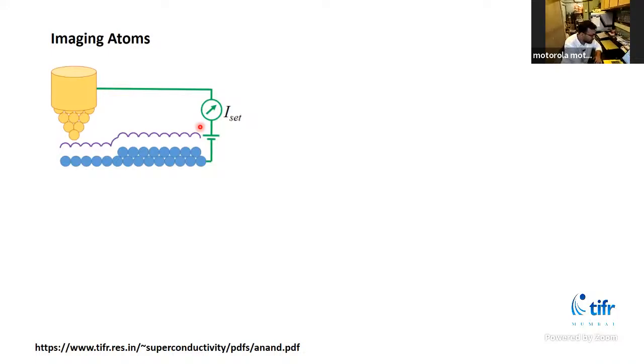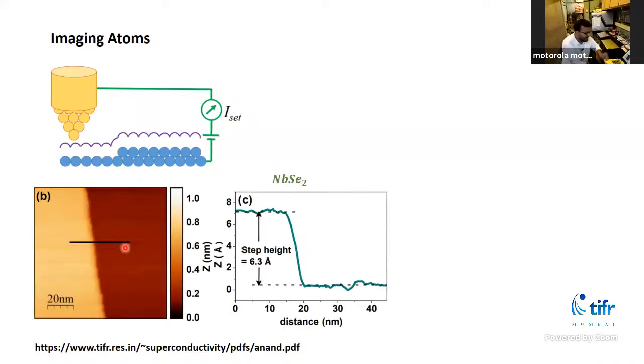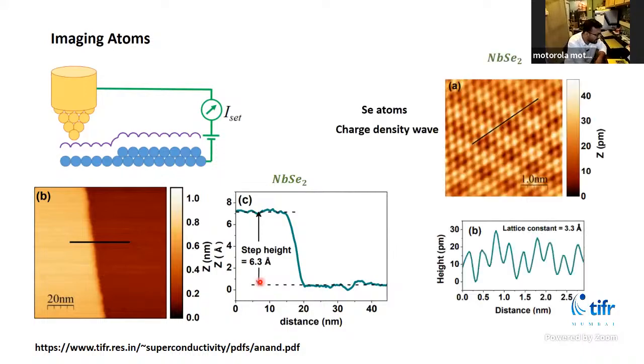And this is what we use. For example, here the material is niobium diselenide, and I have shown you the edge here. This sample has an edge, and if you go from the left hand side to the right hand side, your profile Z will be measured out like this, and you can see the step. Now, to further image these atoms, I will show you the atomic image that we have captured in our lab here at TIFR on the same material, niobium diselenide.